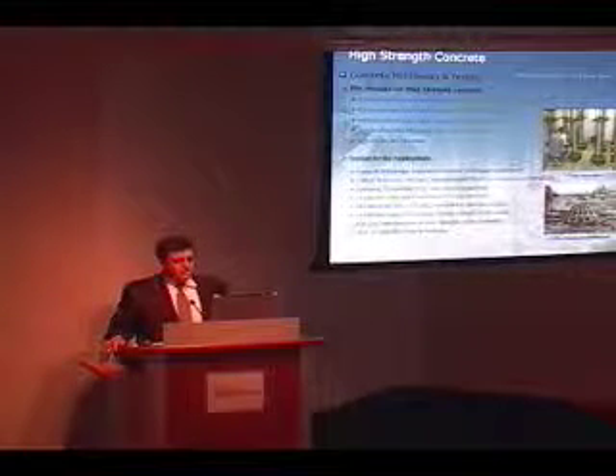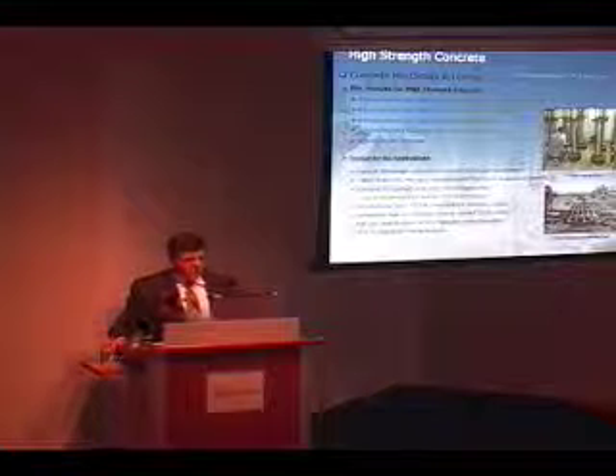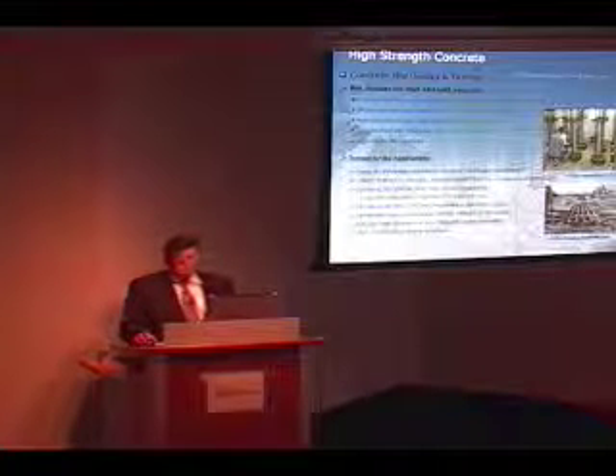Some of the tests that we had done before we started any construction whatsoever are creep and shrinkage testing, evaluation for creep coefficients in order to understand exactly what the behavior of the concrete is, what impact it has on the vertical deformation and also lateral deformation of the tower. And we conducted 2 types of tests, one done at CTL in Chicago, and the other one was done at Samsung Laboratory as a supplemental test. And the results were very close.